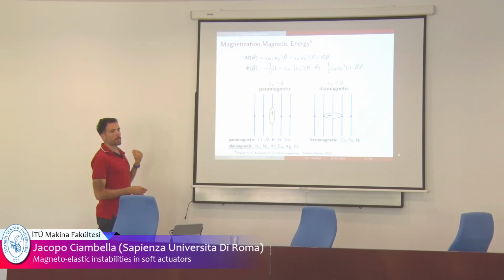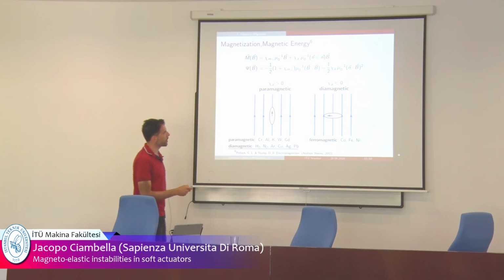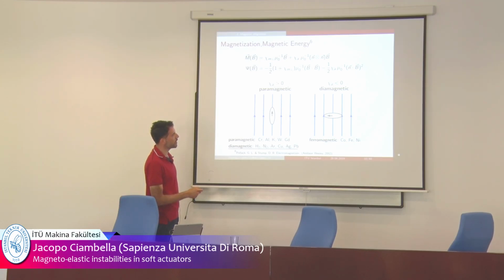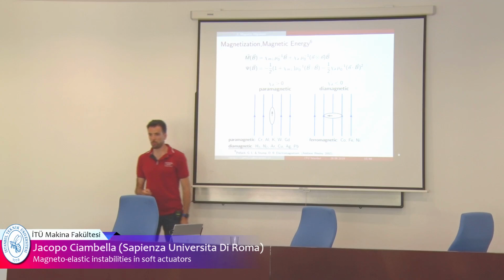So in this setting, you can define the magnetization of the particle, which of course depends on the induction field, as this expression here, where B is the external field. These are material coefficients. Mu 0 is the permeability of the vacuum, as usual. n is the direction of the particle. This is the dyadic product, by the way. And then you can also define the magnetic energy of the particle, which has two terms here. One only depends on the intensity of the field, B times B, this is the inner product. And the other one depends, as I said before, on the inner product between the direction of the particle and the field. This coefficient here is called anisotropic susceptibility, and different materials can have different anisotropic susceptibilities.